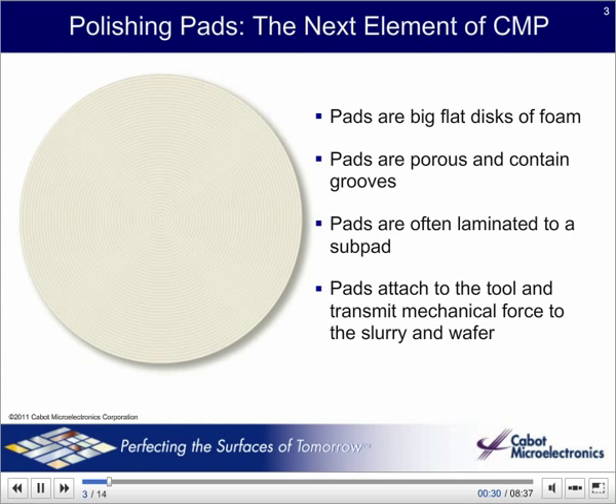Pads are the next big part of CMP. They are usually made of a hard polyurethane foam, are cut into discs, and laminated onto a subpad. Pads have circular or crisscross grooves on the surface. Sometimes pads come with windows that allow sensors to monitor the polishing process. The pads attach face up to the rotating platen on the CMP tool and spin at around 100 RPM.